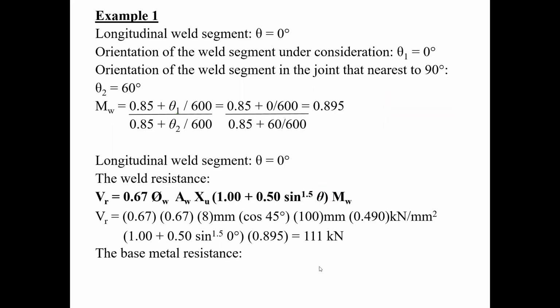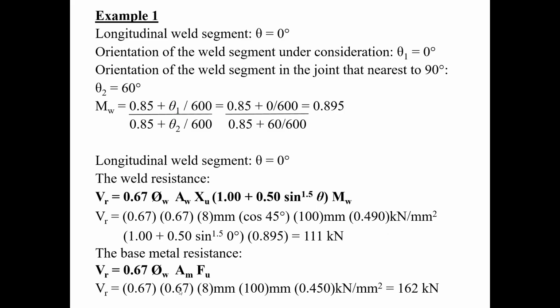Now, this is the equation for the base material. Of course, for the base material, you have to remember 0.67, 0.67. In this case, the height of the leg where the base material is being fused is 8 millimeters, and 162. So it's not the base material that's going to be weaker. It is the weld itself. Therefore, it's the lower of the two. The VR is 111 kilonewtons for the weld segment that is at 0 degrees.